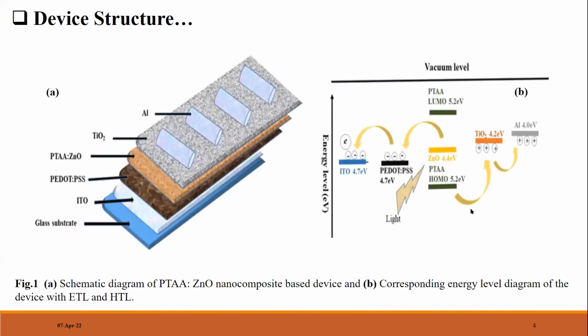This is the schematic structure of my device. Here in this figure you see a glass substrate, and over the glass substrate ITO, a conducting material, as the anode. Over it, PEDOT:PSS, PTAA, ZnO, and TiO2 are deposited layer by layer through a solution process like the spin coating technique, and then finally another electrode, aluminum, as the cathode, will be deposited through the thermal evaporation unit.